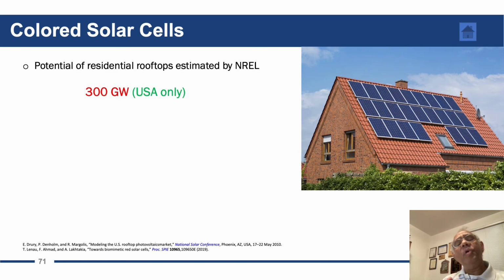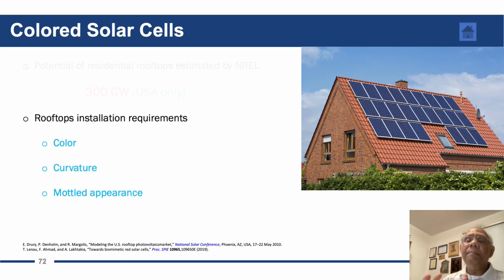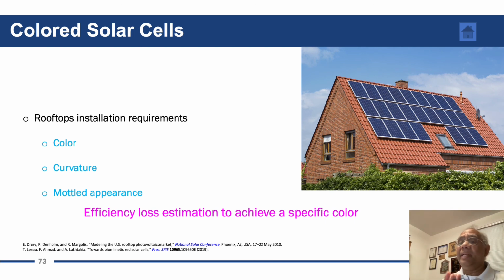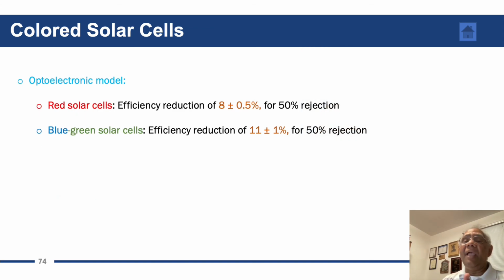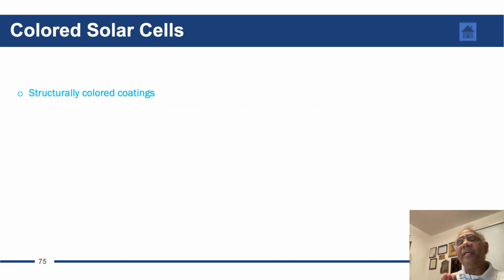Now, the National Renewable Energy Laboratory has estimated that 0.3 terawatt generation capacity is possible using just rooftop solar cells in USA alone. But that means that the rooftop solar cells shall have to have desirable color and curvature, and they must have a mottled appearance to match roof tiles. Colored solar cells will be less efficient, however, because photons of certain colors will have to be reflected. Efficiency will be reduced by about 10% according to our model if 50% colored photons are rejected. Structurally colored coatings can provide that capability.